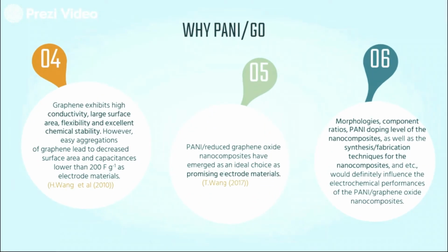So here comes an idea that we want to mix PANI and graphene oxide. Graphene exhibits high conductivity, large surface area, flexibility, and excellent chemical stability. However, easy aggregation of graphene leads to decreased surface area and capacitance lower than 200 farad per gram as electrode materials. So that's why, based on previous research by T. Wang 2017, PANI reduced graphene oxide nanocomposites have emerged as an ideal choice as promising electrode materials. But this idea is actually new, which leads to new limitations to be discovered. So that's why we've come up with an idea, which is PANI and graphene oxide can be chosen as counter electrode replacing the platinum.